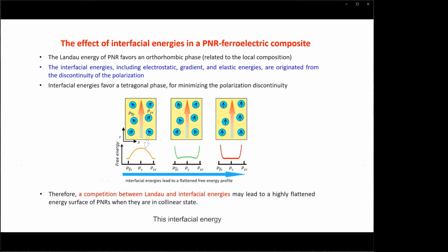This interfacial energy favors the tetragonal phase of those polar nanoregions, because when they transform to the tetragonal phase, the discontinuity of polarization can be minimized. So there is a competition between interfacial and Landau-Bock energies for those polar nanoregions. As shown in this figure, when the interfacial energy is high enough, a highly flattened free energy profile could be achieved for the polar nanoregions. At this time, these polar nanoregions can be very easily rotated by external electric field or stress.